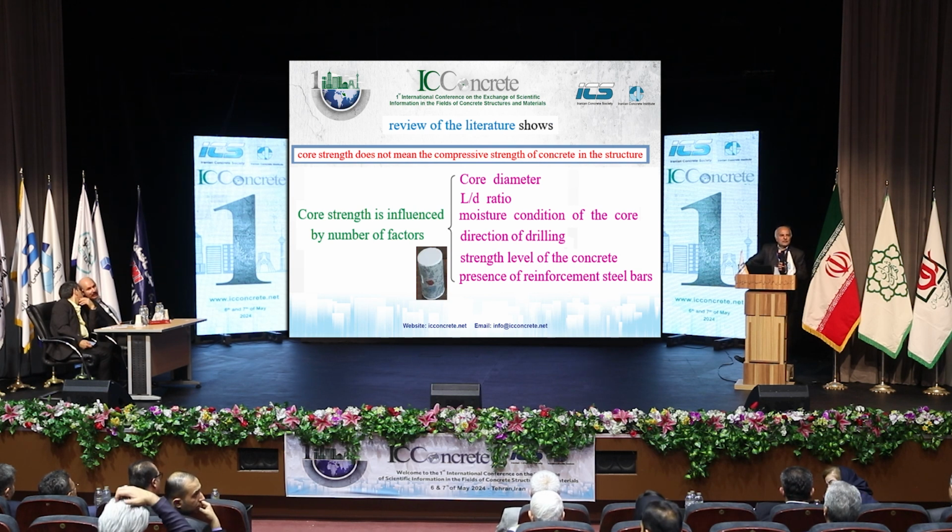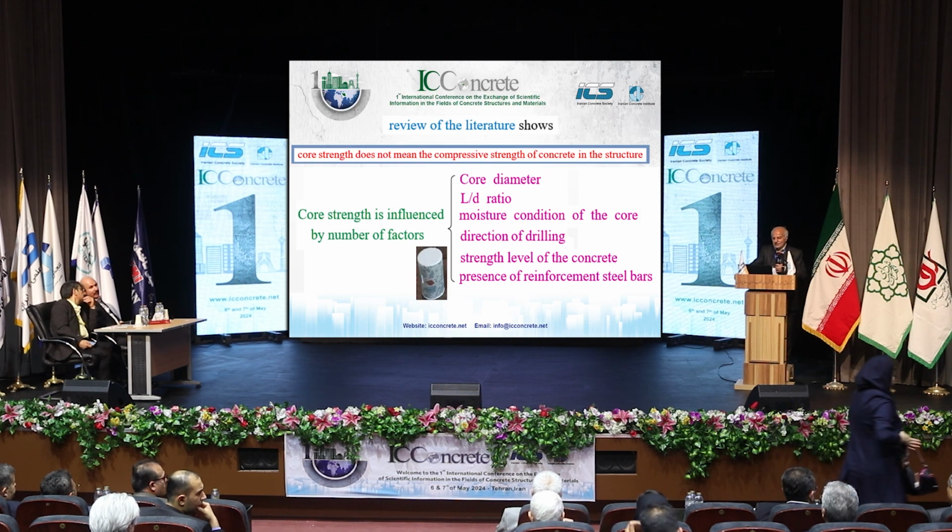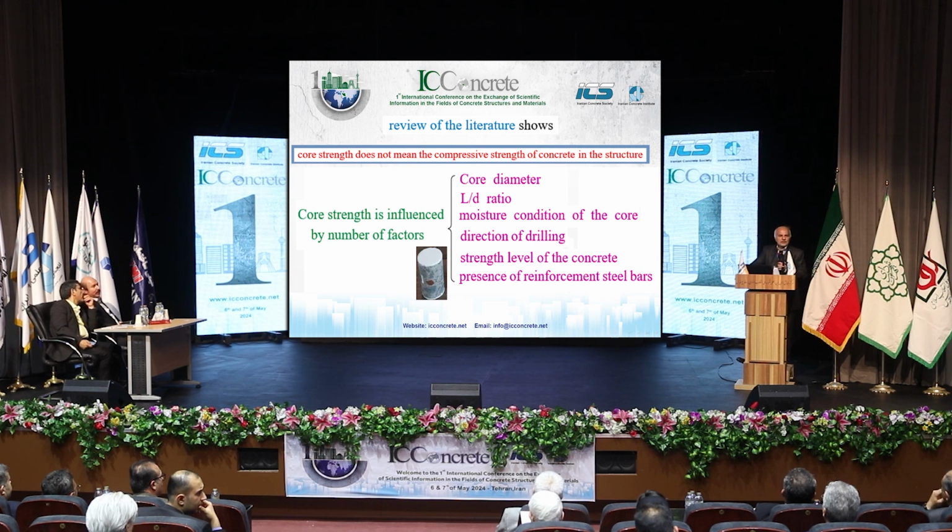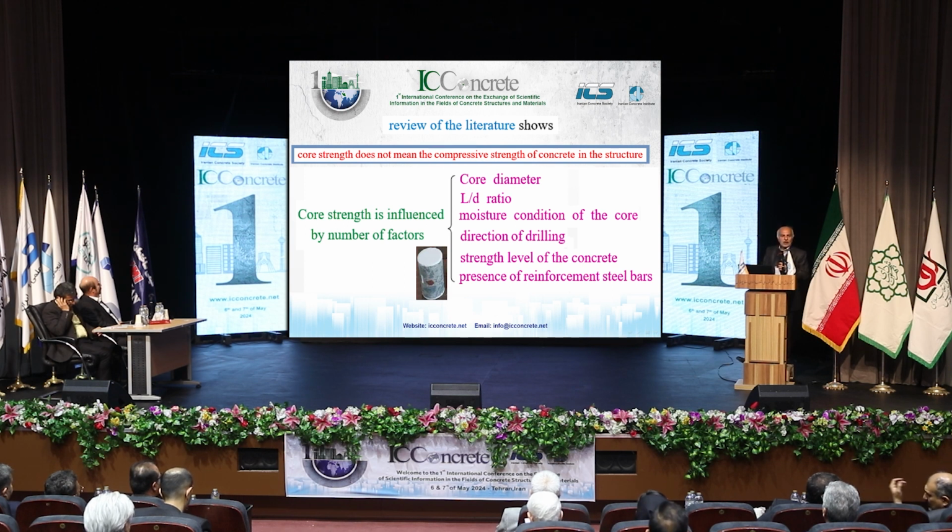From the literature, core strength does not mean the compressive strength of concrete in a structure, for many reasons. As you see, a number of factors influence the core strength, such as core diameter, L/D ratio, moisture condition of the core at the time of testing, direction of drilling, the strength level of the core concrete, and the most important, the presence of reinforcing steel bar.